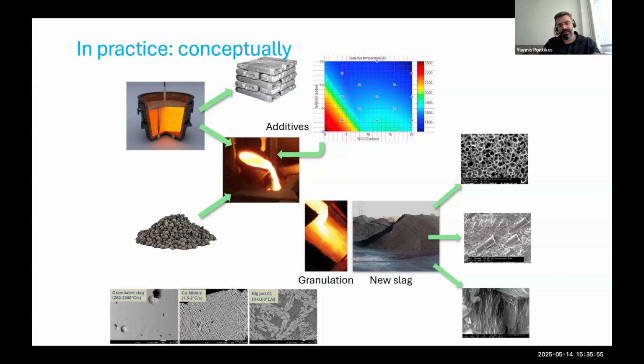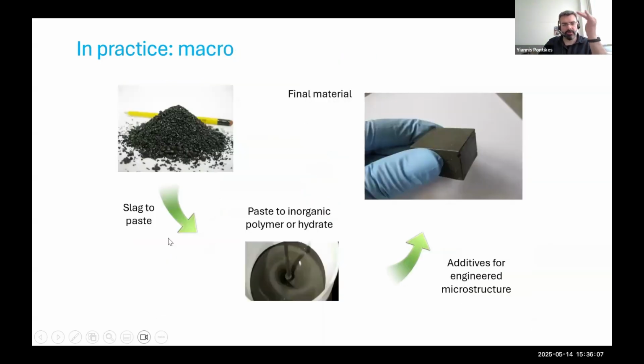In some cases, you want to have aggregates, and I think this makes more sense if you want to have aggregates. But if you want to have a binder, quite often this is preferable. It's not necessarily that you need 100% amorphous. And again, conceptually, you go from this black to this black to this black: powder, slurry, and eventually product.